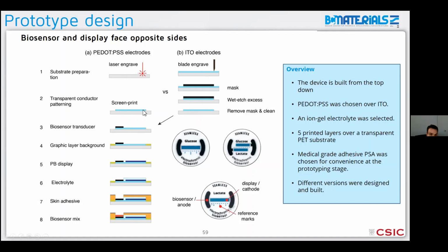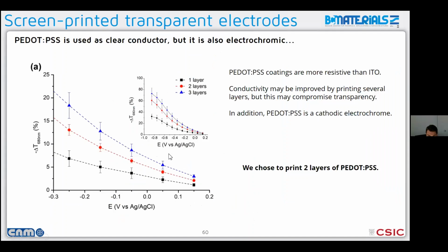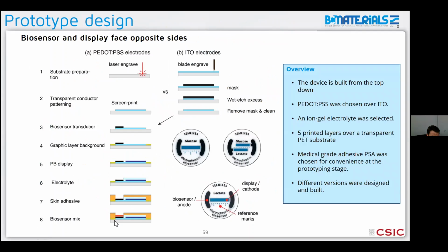Then after screen printing the PEDOT, we print the biosensor, the transducer. This is just graphite. The graphite is also used to make the text in the prototype. Then this background is a dielectric paste. It's just white in color. Gives you a nice contrast both with the text and with this Prussian blue display. And then we printed the electrolyte on top. After this, we put the adhesive, which can either be screen printed or you can use a pressure sensitive adhesive, which is what we did. And then finally, you modify the working electrode, the transducer, with your biosensor mixture. So this was the plan.